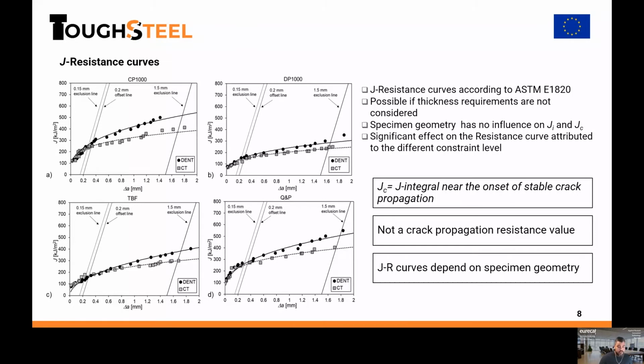So in turn, this plastic work depends on the constraint level, so it depends on the specimen geometry. But interestingly, these initiation values, Jc, as determined at the onset of crack propagation, are quite independent of the specimen geometry. So, in summary, using alternative specimen geometries, we can apply this J integral procedure as described in the standard and determine this Jc.